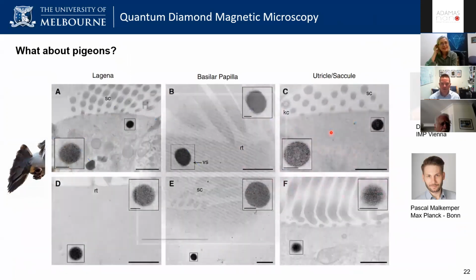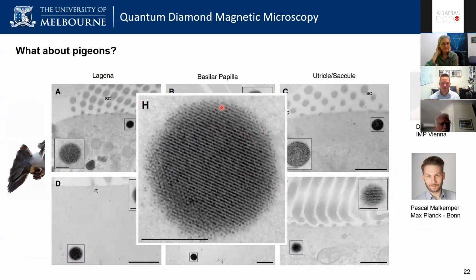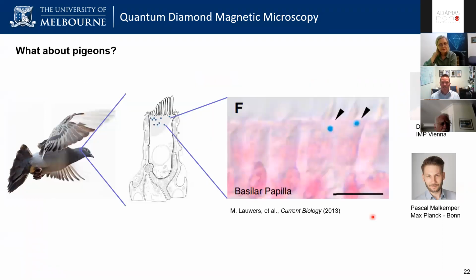When you look at the particles, sometimes the particles look like this, and this is almost a quasi-crystalline structure. You can see it more in that image there, these individual black dots are assumed to be ferritin molecules. So these ferritin proteins are getting assembled into this big ball, and the ball reaches the maximum size of about 400 to 500 nanometers. And we don't see much bigger than that. And so one of the suggestions is that these are just an iron storage mechanism.